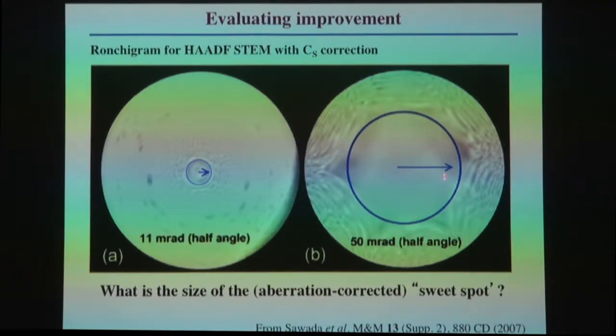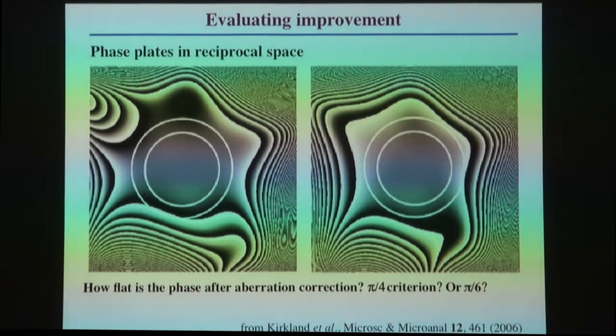And you can say, okay, I could believe that aberration correction is working out to about that particular scattering angle in reciprocal space. So this comes back to the question about how flat is your phase? Do you want to use a pi over 4 criterion? What's the problem with a pi over 2 criterion? The pi over 2 criterion says that anything that was intense, if you had a maximum, would be zero. So how far can you go? Can you go out to pi over 4? So some optimists would use a pi over 4 criterion. The pessimists in the community say, I want pi over 6.